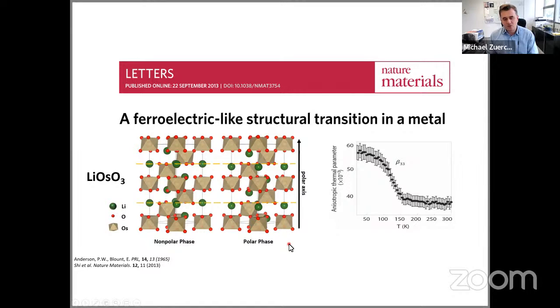So in its core, it's a metal, but at the same time, it has a permanent dipole moment once it undergoes a phase transition here around 150 Kelvin. And so that makes this a kind of interesting material because these are actually contradicting properties, right? Ferroelectricity comes from local dipoles in each unit cell that start to form long-range order. So you have a long-range order of electric dipoles. However, if you have a metal, you would think that free electrons would roam around and start to screen those dipoles. So there should be no long-range order, really. So this was thought of as contradicting properties.